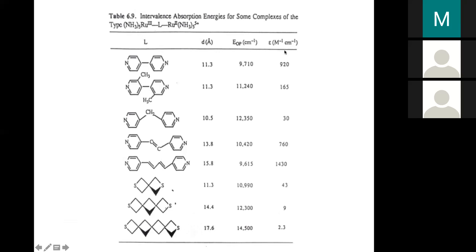So we get an intensity here of close to 1,000 for bipyridine. If we put methyl groups on the pyridine rings, the sterics of those methyls cause the pyridine rings to prefer not to be coplanar. And that drops the intensity because it's weakening the mixing of the two states. And therefore, we have a less intense metal-to-metal charge transfer. If we put a saturated methylene spacer between the two pyridines, this is essentially an insulating barrier, and you can see that band intensity gets really small. This is very close to what might be considered a class 1 compound.